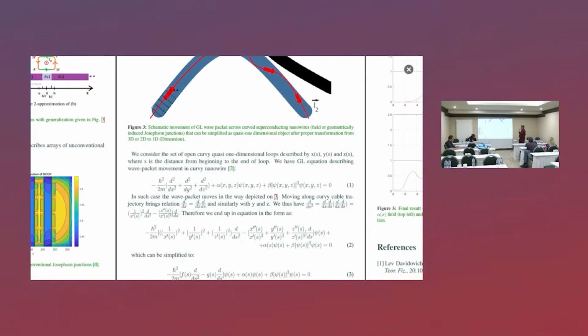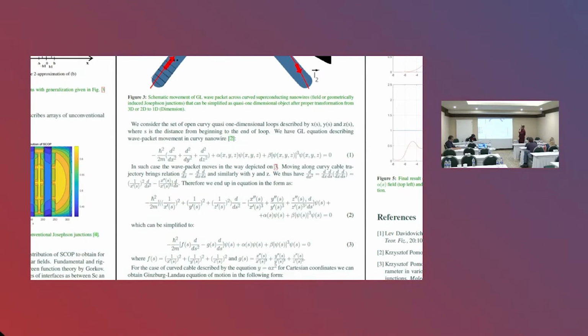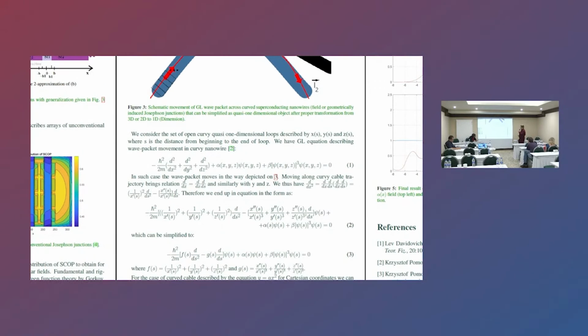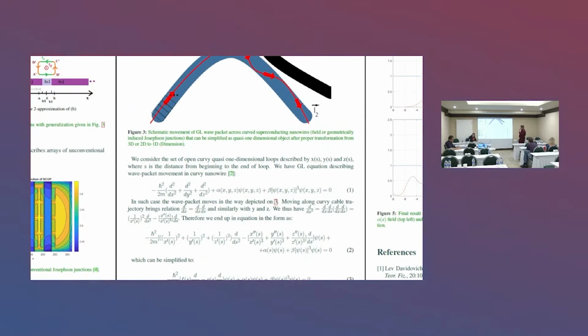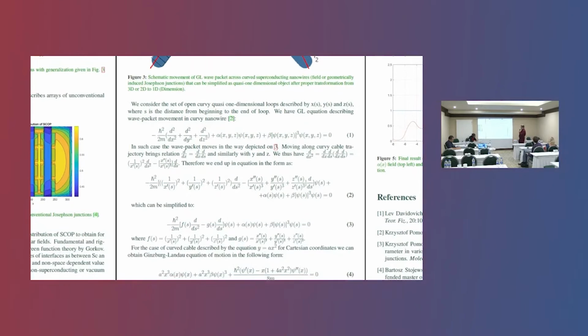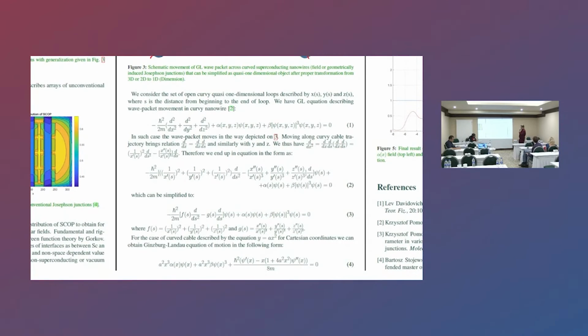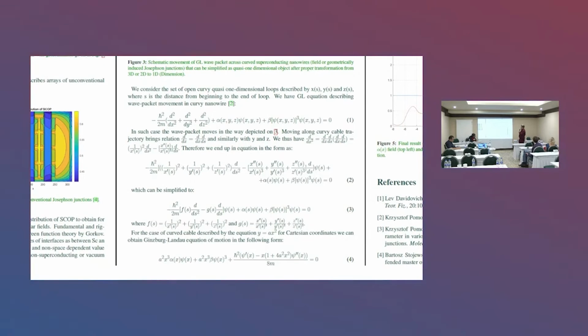So we have 3-dimensional Ginzburg-Landau equation, but these operators can be defined by S parameter. So effectively, the 3-dimensional equation can be reduced to quasi 1-dimensional of this form, where the curvature is encoded in these functions. So can we go down, please? Go down, yeah. So we finally end up in such type of equation. So we have this F and Fs and the GS functions that encode the curvature of a system.